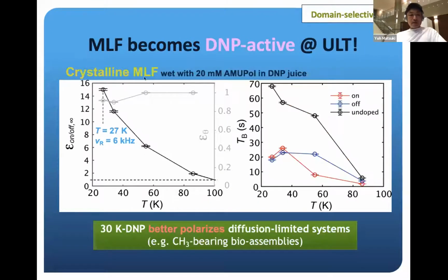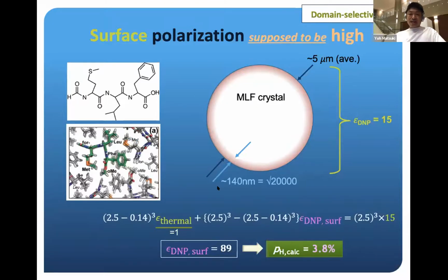So here you go, the enhancement factor for MLF, it's really picking up with dropping sample temperature, reaching a factor of 15 or so at 30 Kelvin. The build-up time constant was around 20 sec at 30 Kelvin. So in general, 30 Kelvin DNP polarizes these real samples, like methyl-loaded sample, much better than conventional 100 Kelvin DNP. Well, the enhancement of 15 sounds not too impressive, you might say, but you have to remember that within this 20 sec or so build-up time, the polarization is only allowed to sink into the crystal by 130, 140 nanometers or so from the crystalline surface, leaving largely the crystal core at the thermal equilibrium state.